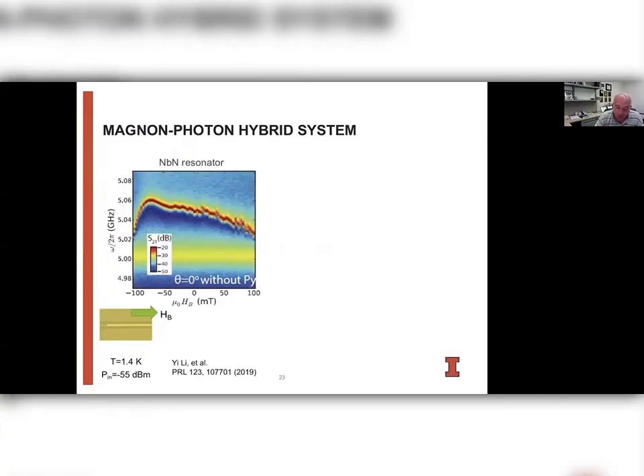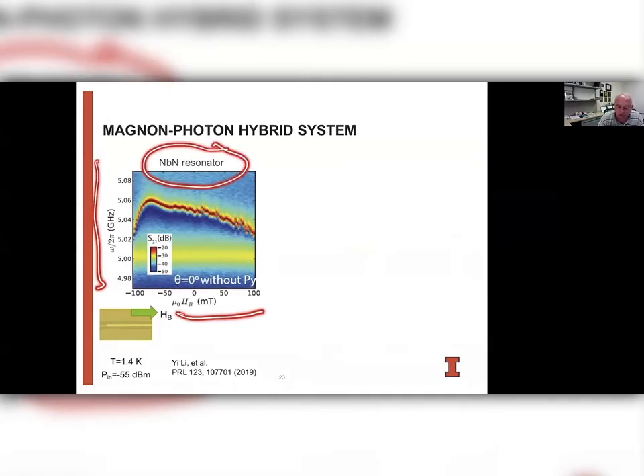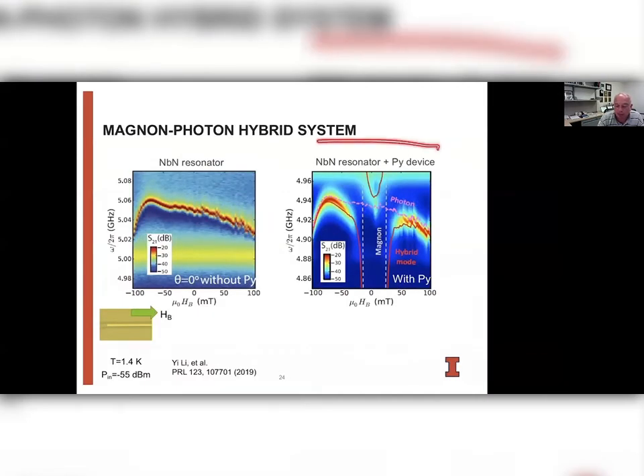Now, we can go back to the complete magnon-photon hybrid system. Just as a reminder, this is the resonance frequency as a function of magnetic field for just the niobium nitride resonator on its own. And if we compare this now with the niobium nitride resonator where we have the permalloy device integrated, we see that we now have a distinct mode splitting that occurs right in the region where the magnon branch crosses over our photon dispersion that we have in our oscillator. So we see this distinct splitting between the modes here.